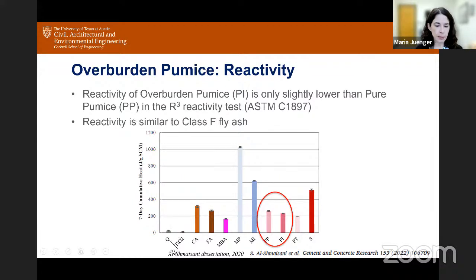So these gray materials here on the left are quartz, which is Q here, and titanium dioxide. You expect that these are not pozzolanic, so therefore they have no heat. So that's really just a check against an expectation. If we look at the fly ashes, the CA and the FA that I showed earlier, and we look at the pumices, the PP, again, silly names, but this is what they have. PP is pure pumicite. PI is impure pumicite, so the overburdened pumice. They actually have a very similar reactivity to the class F fly ash in this particular test method. So it's really not so different in this particular test method, and the impure pumice is not so different than the pure pumice, which is promising in this test method.